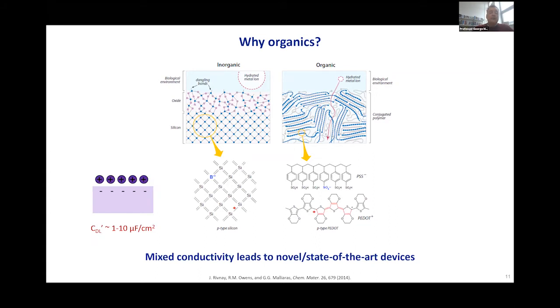In materials where you can remove that oxide, for example, if you use platinum, gold, or another noble metal electrode, you're going to arrive in a situation where you have ionic charge on one side of the interface and electronic on the other. And their coupling takes place along an interface as indicated here. This gives you fairly limited communication between the two worlds, the world of ionics, of biology, and the world of electronics. And this is described by the so-called capacitance, where the double layer capacitance, which is of the order of 1 to 10 microfarad per square centimeter.